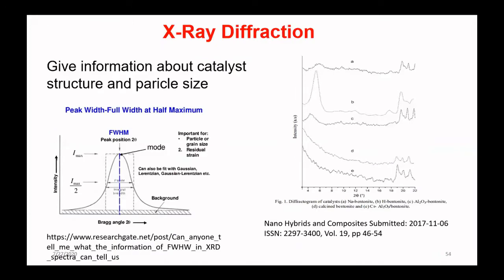For example, on the right side, this is our research, my student. Prepare alumina bentonite pellet. So we can see on the right side, this is bentonite, before activation, sodium bentonite, and after activation with acid, through a chemical and physical process, we obtain a very good peak, representative of the 001 interlayer of clay, or basal spacing. And then we insert it with alumina. There is a shift of the peak, so we can follow the process using XRD.